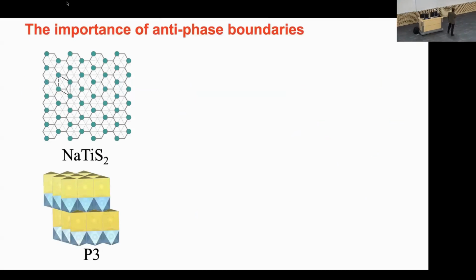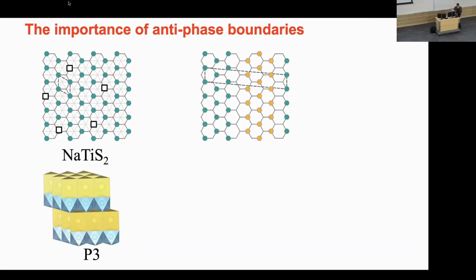And that leads to interesting ordering phenomena. So let's say we have this network like this. This is the P3 structure. You have this honeycomb network. And when you have sodium TiS2 in the P3 structure, every other site of the honeycomb network is filled. So you've got a filled, empty, and so forth. And when you pull sodium out, you're going to leave behind vacancies. And so normally in most of these battery materials, like O3 and lithium battery materials, you create vacancies, and they entropically spread out. They don't want to really cluster together, and they also repel each other energetically. So that's what you would normally expect. But on this honeycomb network, the topology of the network causes interesting things.